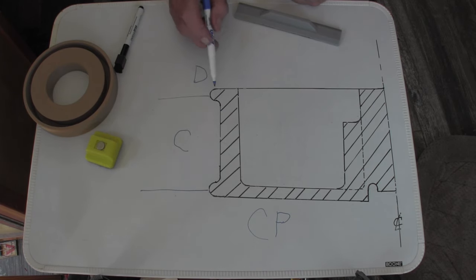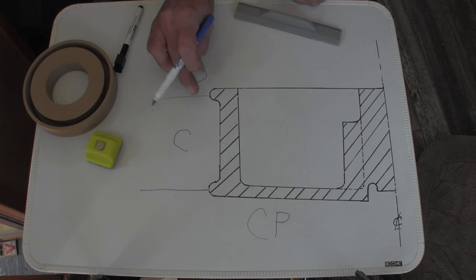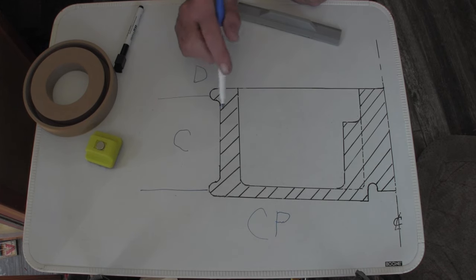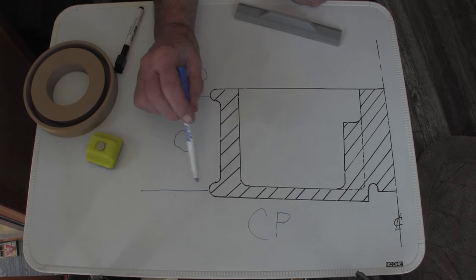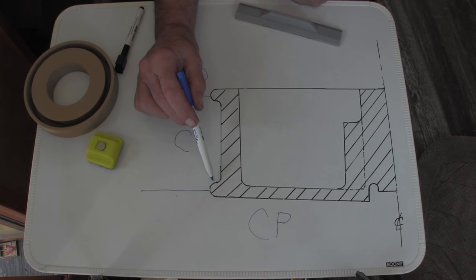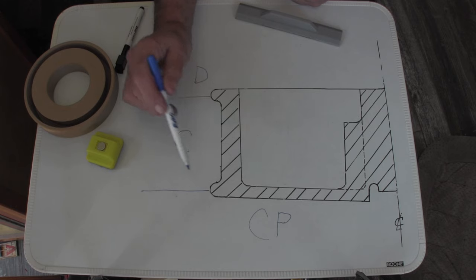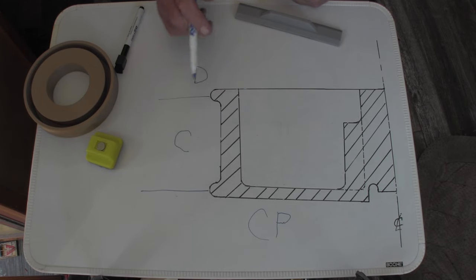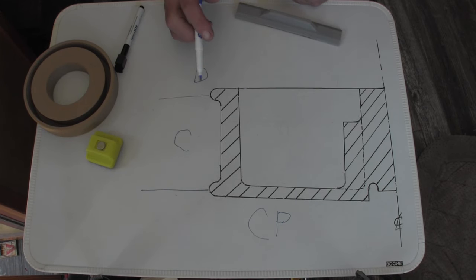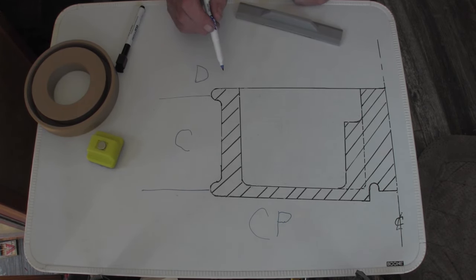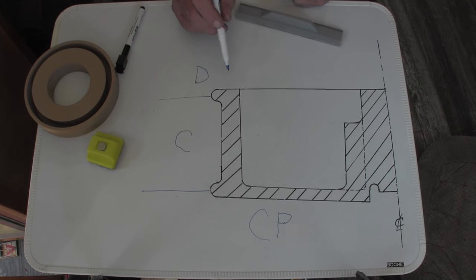This would come out, but you got a problem. This side is okay because this is, and this would be fixed. So everything up to here would be solid, but you cannot pull this out because you have this little lip over the top. So you can't just pull it out of the cheek or pull the pattern out with the cheek there. You can't separate them, basically, is what I'm trying to say.